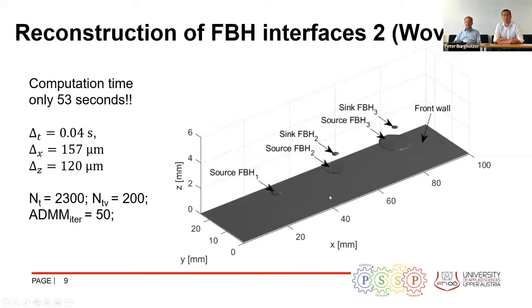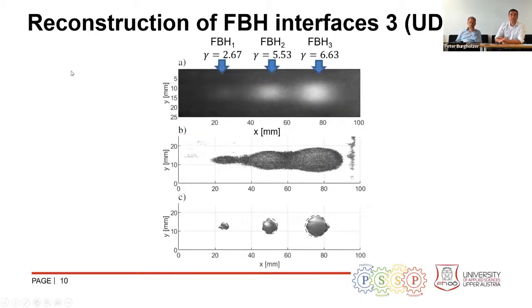Yeah, and with the virtual wave concept, it is called tomography, you are also able to do some 3D reconstruction of these internal defects. And this is the first time worldwide that it is possible to do this 3-dimensional visualization of the internal defects by temperature data. And this is also very fast, only 1 minute for the calculation of the whole image.